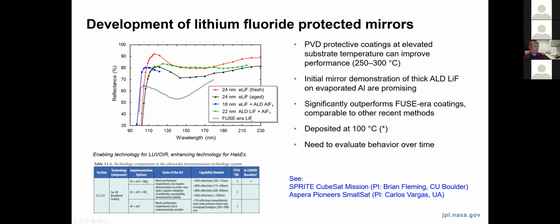Since FUSE, there's been a lot more work at understanding this problem with lithium fluoride. It really has to do with the hygroscopic properties of lithium fluoride and its reactivity with water. So that tends to result in this degradation in reflectance as a function of time after the coating has been fabricated.